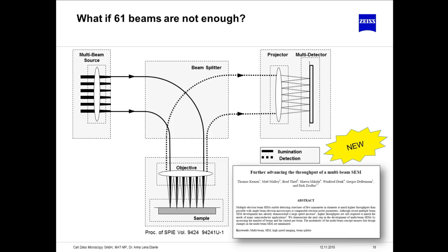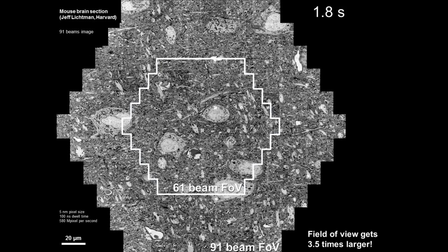Now, with this 91 beam multisem, it's not that we added more beams to the field of view. We also increased the distance between the beams. So the actual field of view of the 91 beam version of this tool is about 3.5 times larger. And by this, it actually increases the throughput by more or less this factor as well.